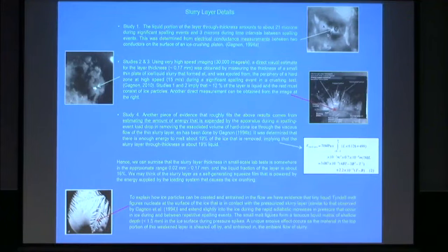So from all those pieces of information, you can determine that the slurry layer for the lab tests at least is between 0.02 and 0.17 millimeters, and that the liquid fraction is about 16%. And then the question is, how does that slurry layer form if it's 80% solid material?